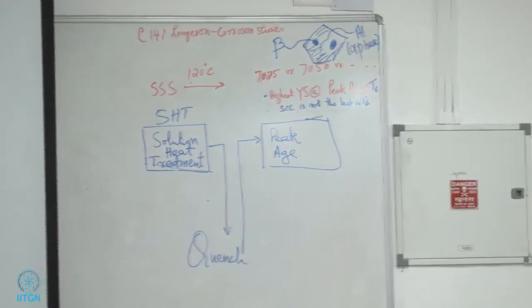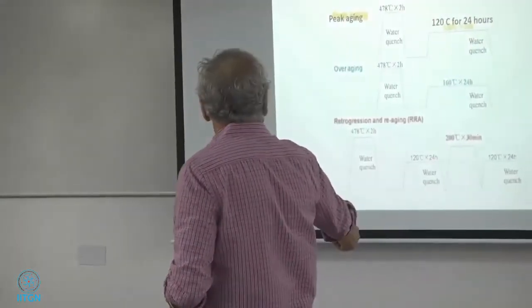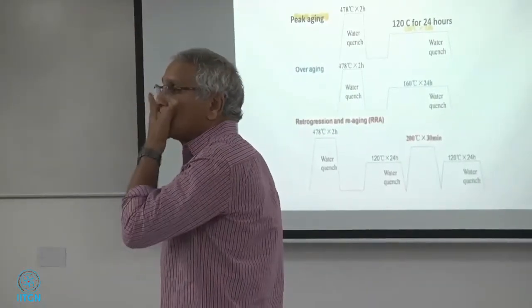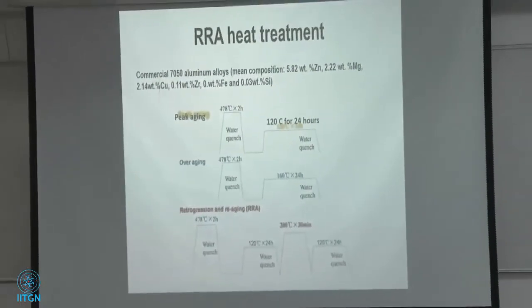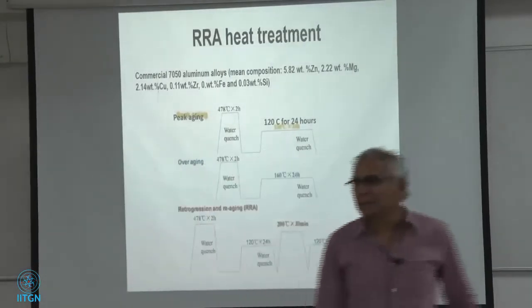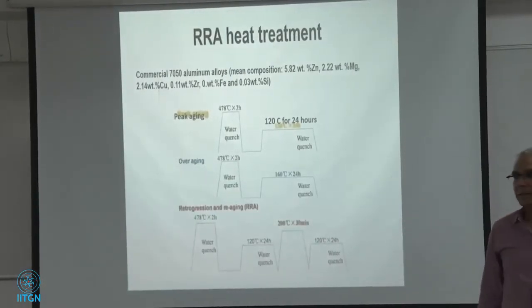Longeron, corrosion. So for something like that, this is a big beam. It's 3 or 4 floors high. I don't know, some of these cargo planes are very big. So if you have to heat treat the whole part, it's going to take a long time. I think they have been doing it with heating tape, because you can't have a furnace that big. And this is not a very high temperature. You can get it with the heating tape. So if you can put the heating tape on the whole Longeron, you can get to that temperature. Yeah, commercial industry things is a different ballgame.